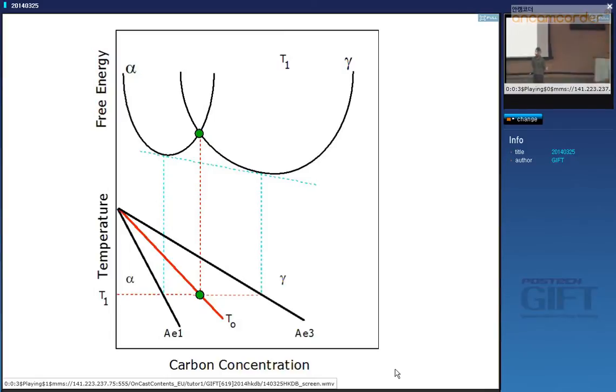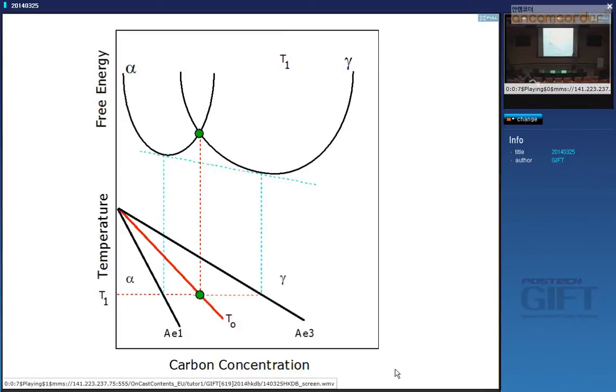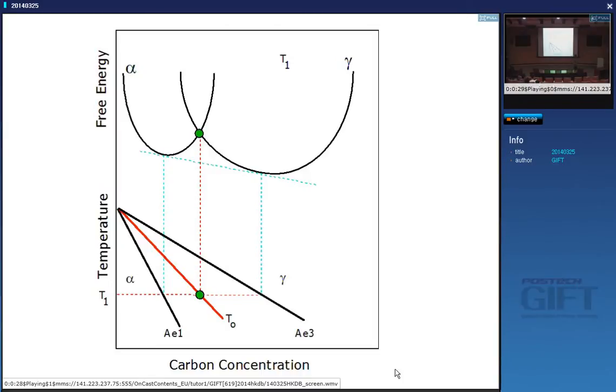Shall we start? Today I'm going to show you how you can use the T0 curve to design some really excellent steels. These curves are now used in many circumstances to study steels and also to design alloys — all of the TRIP steels for example. Just to remind you, these are the free energy curves of ferrite and austenite at a constant temperature T1. Normally when we want to calculate an equilibrium phase diagram we draw a tangent common to both surfaces, and where the tangent touches you get the equilibrium composition of ferrite and the equilibrium composition of austenite at T1. This point here is where austenite and ferrite of exactly the same free energy have the same chemical composition, and the locus of this point as a function of temperature defines the T0 curve.